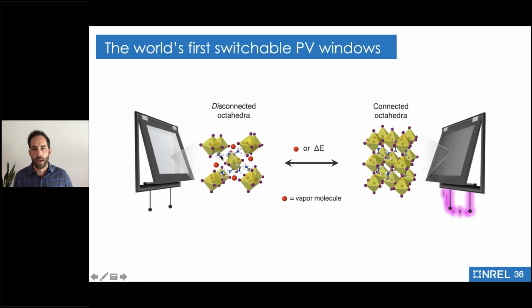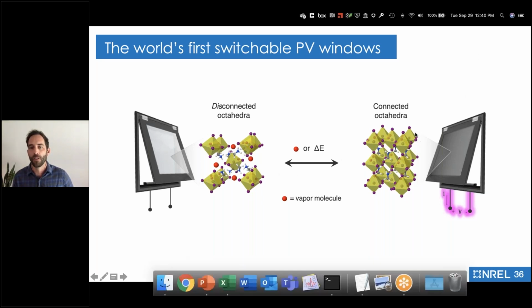And the wrinkle I'm putting on perovskite technologies is we have all these properties that make for a fantastic photovoltaic, and we are changing the color of it. The way we do that, and again, this is really broad strokes for material science, is we take the crystal structure on the right side. When it's all connected, we have all these octahedra, all the iodides are sharing the corners of these things. What happens is you get a very dark material that absorbs very well, and it's a very good photovoltaic material.